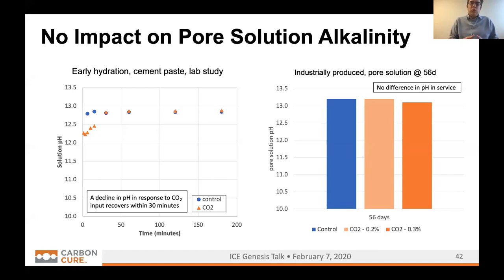So we had to look at what is the CO2 doing to the pore solution pH. And so if we start on the right, nothing. The answer is nothing. So if you look at this addition of CO2 to the concrete, you've not done anything to the pH in service. And we have looked at this by taking concrete samples and taking out the pore solution and actually directly measuring it. And we do not see any difference.